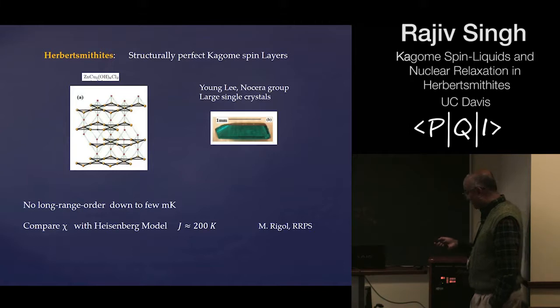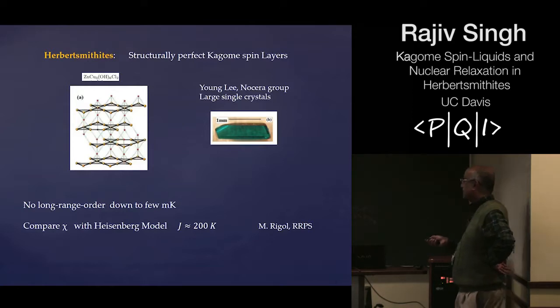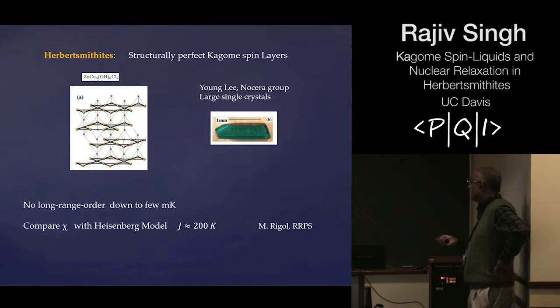Okay, let me just very briefly then talk about the materials. So these Herbertsmithites have zinc and copper transition metal ions. They basically have this pyrochlore structure, which is a layered structure. Ideally all the copper spins form these Kagome lattices and all the zinc spins sit in the middle and form what are called triangular planes in the middle. And if zinc is non-magnetic and copper is magnetic, you have really magnetically well isolated Kagome layers. That's the beautiful green color of copper here.